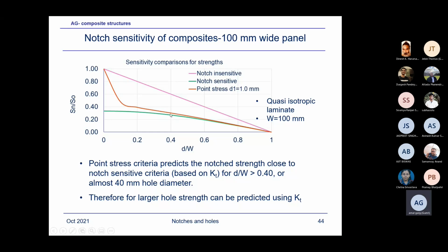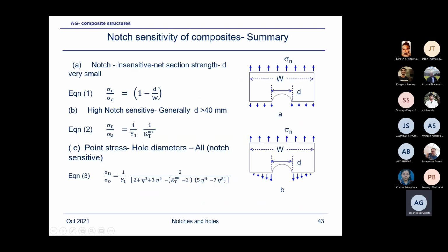So the utility of this behavior is to show you that for holes up to around 25 to 40 millimeters, almost 40 millimeters, we can use the point stress criteria to predict the residual strength. But beyond that, for a larger hole, like beyond 40 millimeter, we don't worry about the point stress criteria. We just use this criteria to predict the notch, hole strength. I'm talking of notch, but it's a hole here. Notch will mean the cracks, sharp cracks.